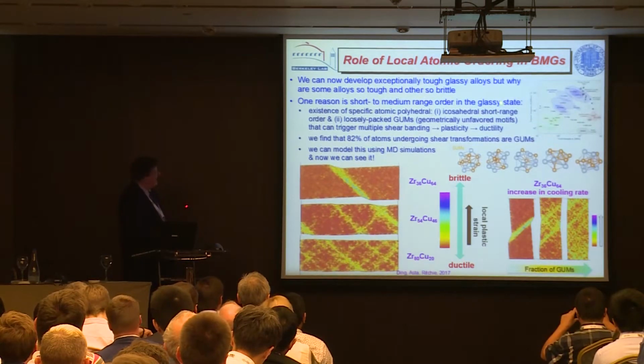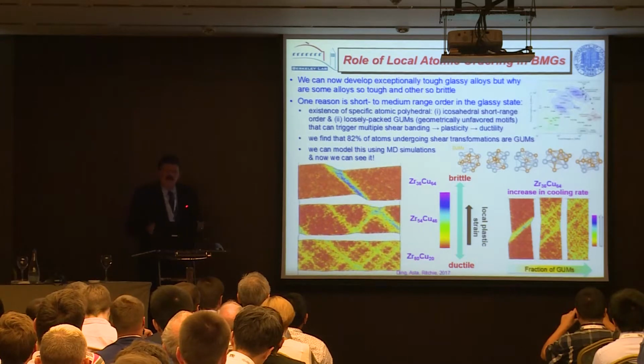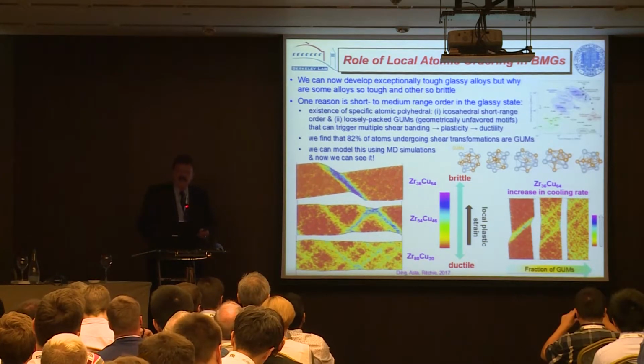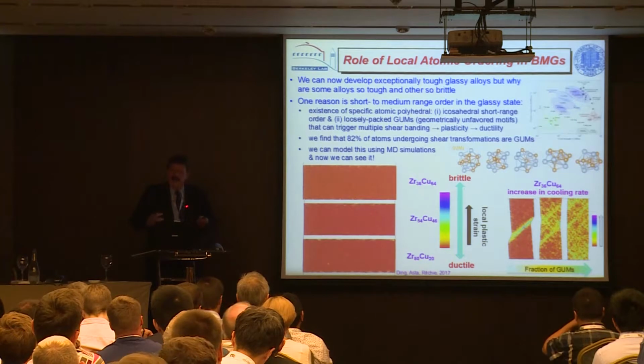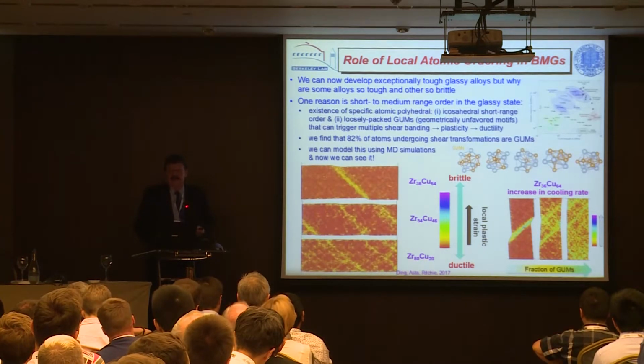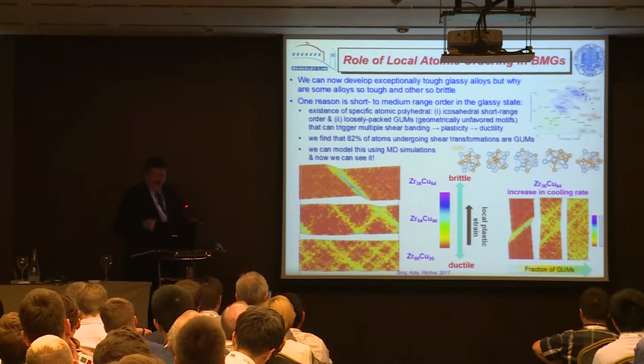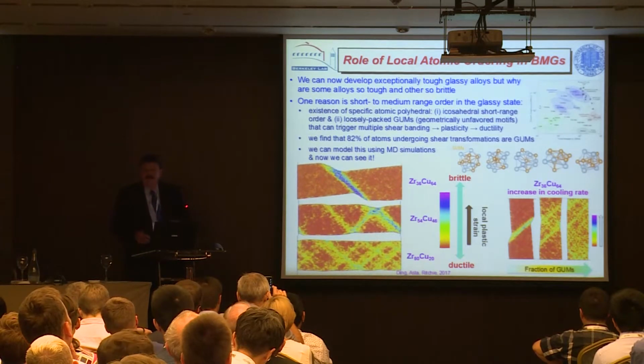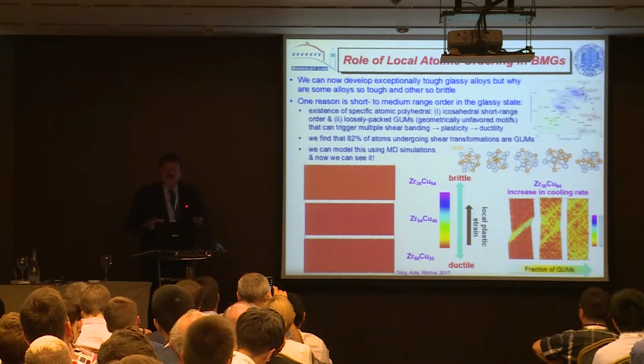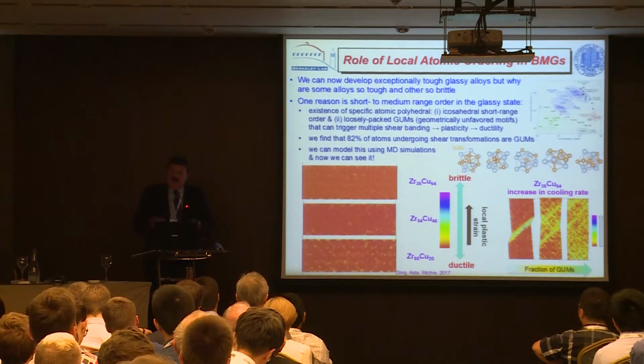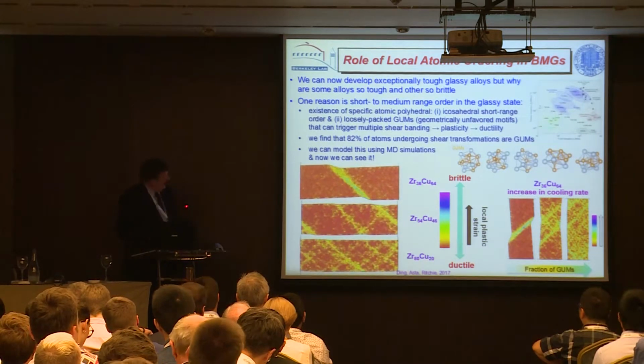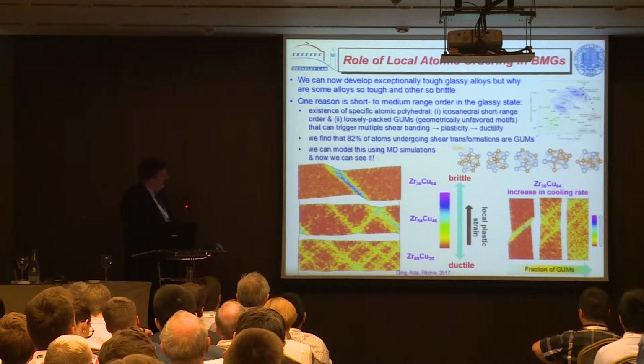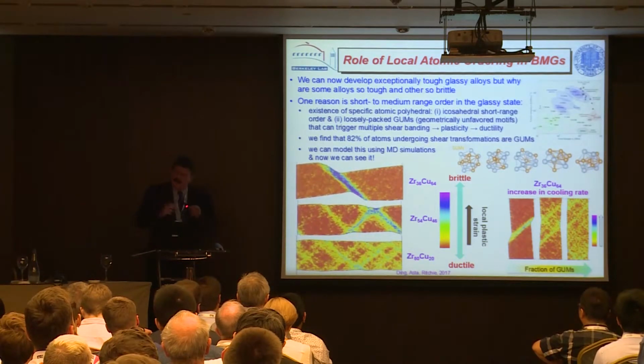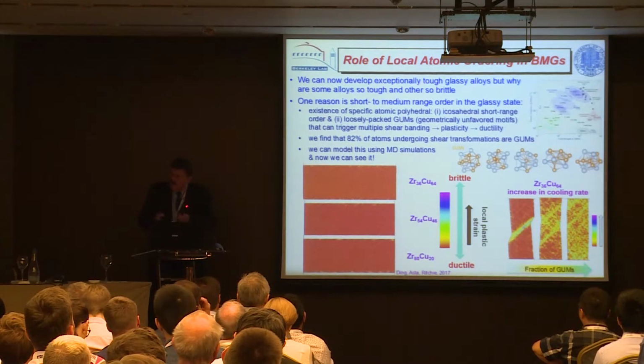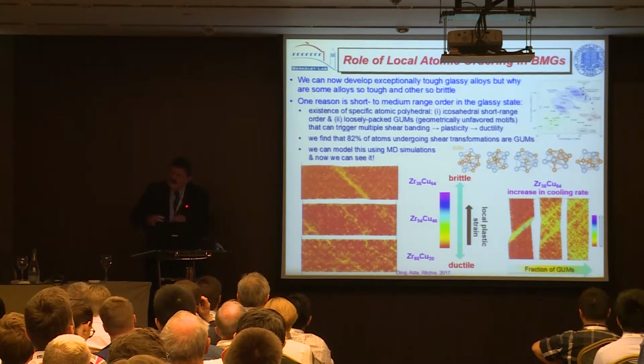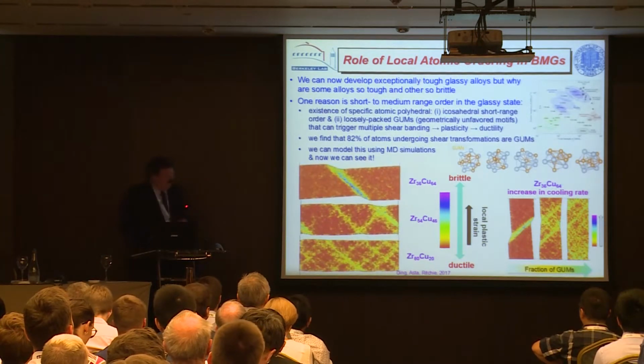And there's a more interesting reason, which I think is more fun, and that is that I think the community now realizes that the amorphous state, the glassy state, is not a single state. That there is some degree of local order in that amorphous state. Now, people like Lindsay Greer talk about nanostructure in the amorphous glassy state. We tend to talk about local configurations or motifs of atoms that form in local order. This is basically local, short to medium range order.